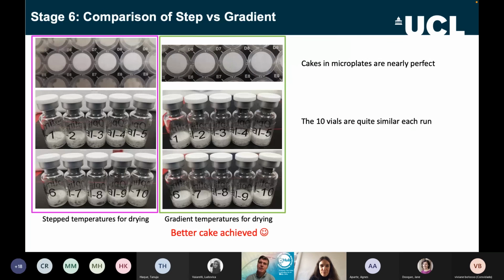Well, I think it might be quite similar because the freeze dryer is a pilot scale freeze dryer. So the vial dimensions are all as you would use them. So they're no different. I guess on a really large scale, I would imagine, if anything, less of an issue because changing the temperature and the pressure in the larger scale freeze dryer would be less abrupt. But how much impact that will have, I couldn't exactly tell you. But I suspect it won't be a massive impact. I think once we've got to this scale in the pilot dryer, it's reasonably comfortable. There may be some fine-tuning to do, of course.